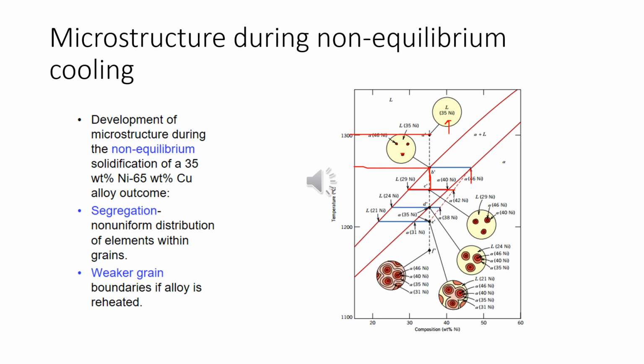However, because diffusion in solid alpha phase is relatively slow, the alpha phase that formed at point B prime has not changed composition appreciably. That is, it is still about 46% weight of the nickel, and the composition of the alpha grains has continuously changed with the radial position from 46% weight of nickel at grain centers to 40% weight of the nickel. The small dash line represents the further diffusion. So further time is required for the cooling.